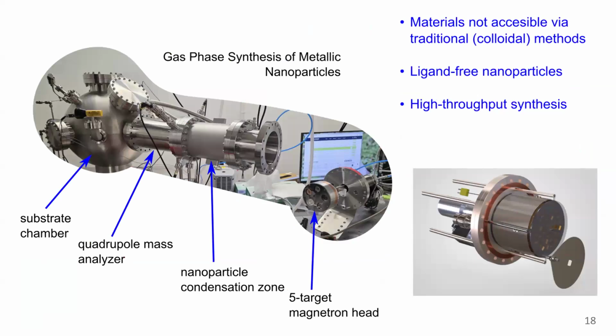So you can buy an installation with a sputtering head on the side. You sputter particles and then sputter them a second time to intentionally make core shell structures. However, if you think about catalysis, in order to have strain from the core affecting the binding energy of the shell, strain will dissipate within a few nanometers. So if you have a shell that's thicker than 1 or 2 nanometers, it's essentially like having a bulk material. A lot of these secondary sputtering sources will make a core shell structure, but that shell is 5 nanometers thick, and it's not going to affect the core. The core and the shell are essentially decoupled.